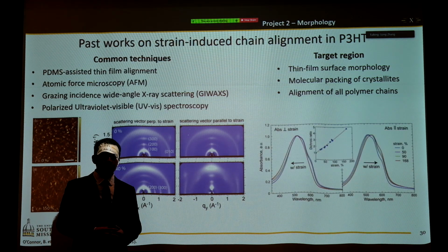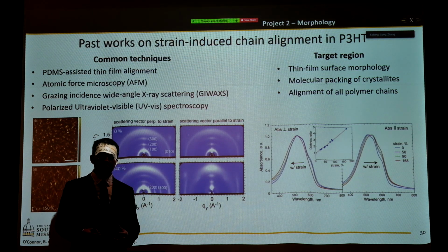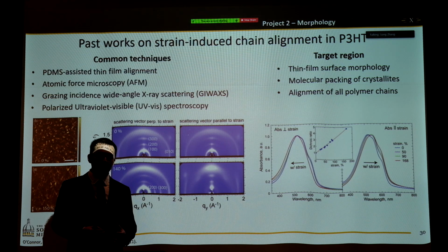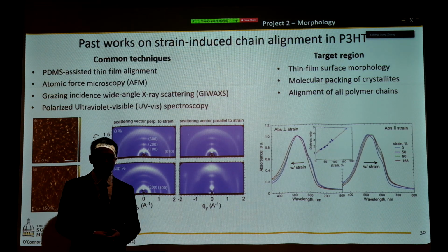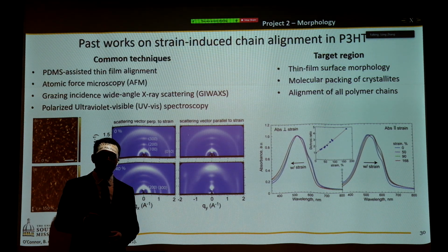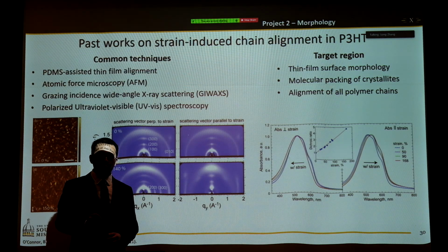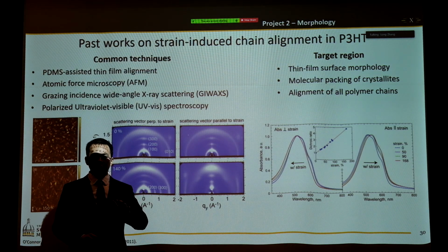Thirdly, by using polarized UV-Vis, which looks at the intermolecular aggregation, it will help us to understand the chain alignment of averaged polymer chains. And that is obtained from the absorbed intensity when the polymer thin film is parallel versus perpendicular.